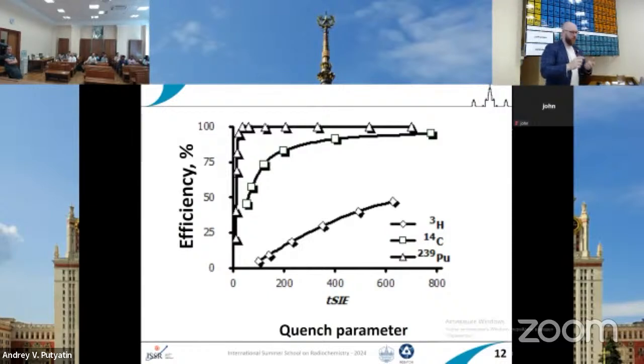So the very good characteristic of plastic vials is that this plastic material makes the illumination homogeneous. So it reaches the photomultiplier tubes, let's say, homogeneously, independent of where your nuclide is located. But it is not the case for glass vials. The glass is more transparent, yes, but you really need to make a precise geometry inside the glass vials to have the same conditions for measurement. It is not the case for plastic vials because they make this homogeneous illumination. So for me, it's more convenient to use plastic.